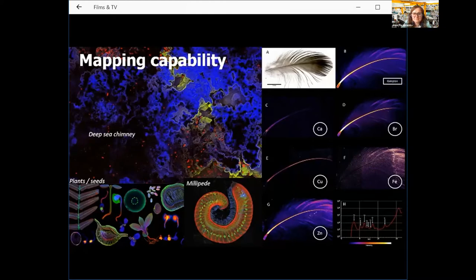We can map at very high resolution, down to 2 microns. And we can also map samples that are millimeters in size to centimeters in size. Even whole paintings or whole plants can be put into this beamline with almost no preparation. For most things, it is better to have a thin section. If you want to get quantitative maps, it helps to know how thick the sample is.